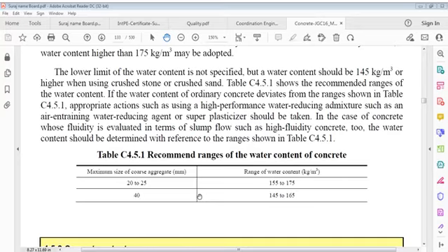The lower value of water content is not specified, but water content should be 145 kg per cubic meter or higher when using crushed stone or crushed sand. This shows recommended ranges of water content. If water content of ordinary concrete deviates from the ranges shown, appropriate actions such as using a high performance water reducing admixture, such as an air entraining water reducing agent or superplasticizer, should be taken, in the case of concrete whose fluidity is evaluated in terms of slump flow, such as high fluidity concrete.